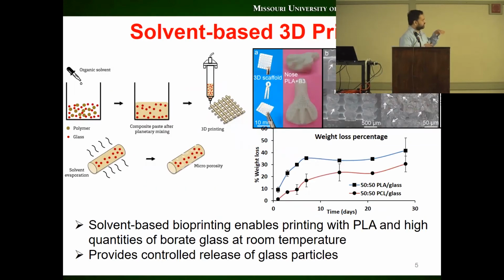So what we do is we take bioactive glass, mix it with the polymer, make a paste, extrude it, and we can print any kind of shapes. In the pictures you see, let's say, a half-built nose. And then the microstructures, what we basically study is how the glass is being released from the polymer matrix. So unlike the commercial bioprinters, we can use different polymers and control the rate of glass dissolution from the polymer matrix. We can use PLA or PCL and control the degradation. We can also use different bioactive glasses.